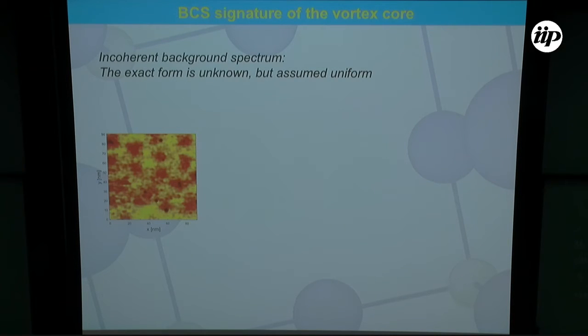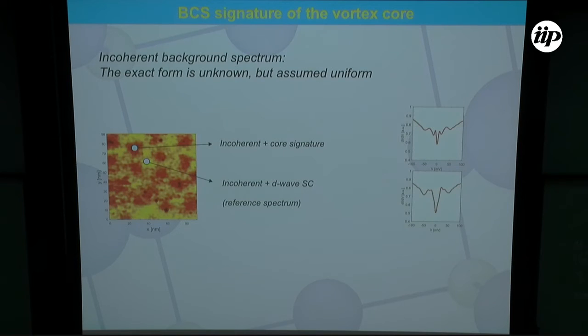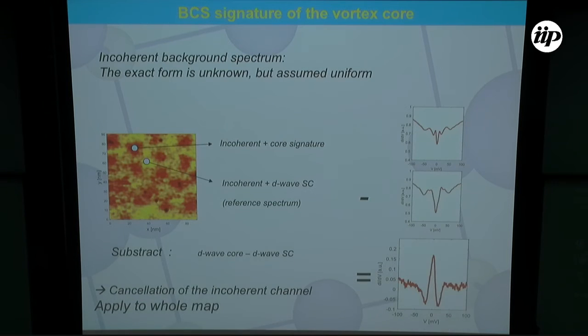So we have the situation where we have this incoherent channel, which is uniformly detected over the surface. Let's do the following procedure. We take as a reference spectrum the spectrum measured outside the vortices, which in our model consists of the incoherent plus the superconducting D-wave part. Then the other spectra, like for example the one measured at the center of the core, will be the addition of the incoherent plus the D-wave core signature. And so, assuming that this incoherent channel is uniform all over the surface, a subtraction of these two will provide you the difference between the D-wave core spectrum minus the D-wave superconducting spectrum.